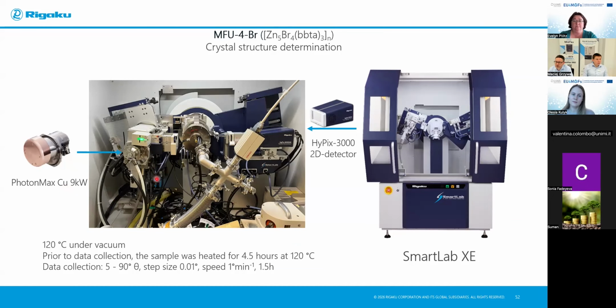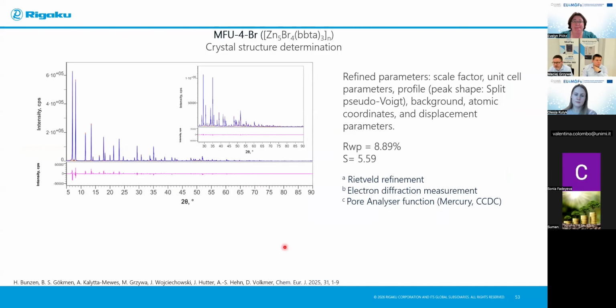In such a case, I collected the data on the SmartLab diffractometer equipped with a rotating anode, also with the high temperature chamber from Anton Paar HTK 1200. Prior to the measurement, I evacuated the sample 4.5 hours at 120 degrees to remove all occluded solvent molecules in the pores. And after that, I collected the data within 1.5 hours. And then I performed the Rietveld refinement.